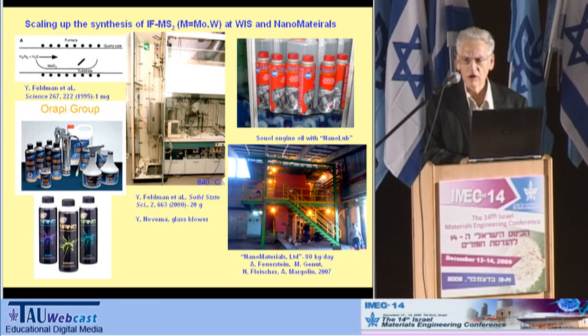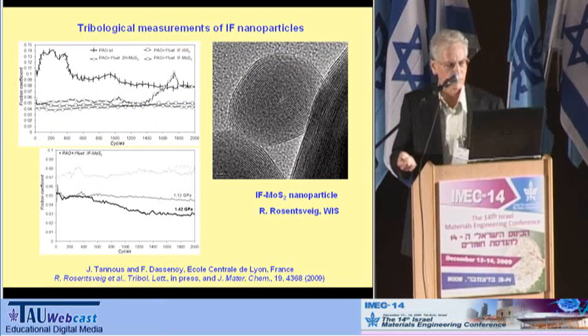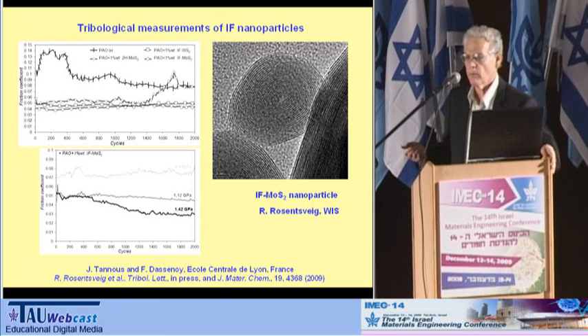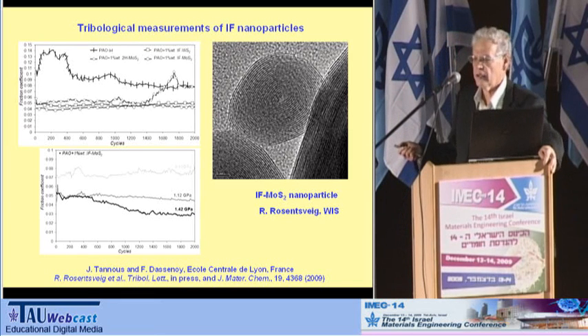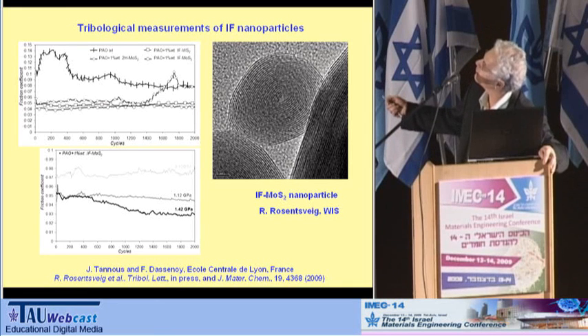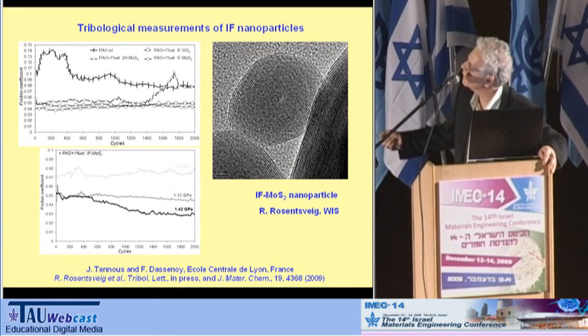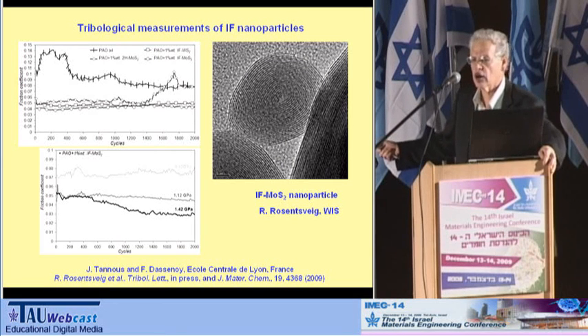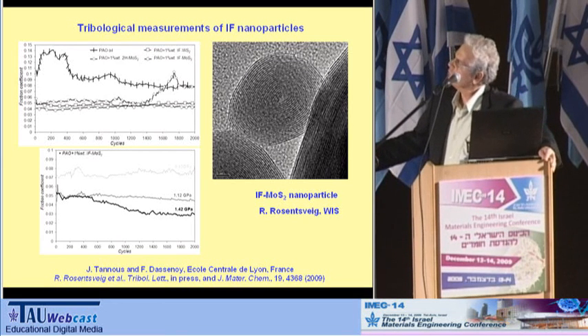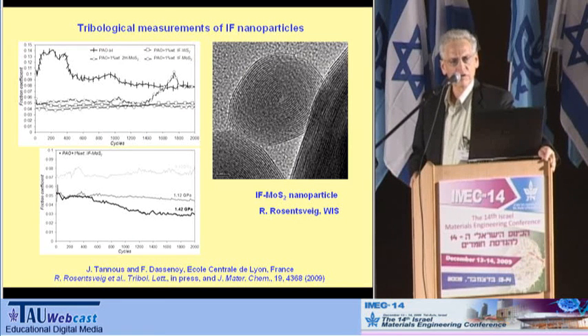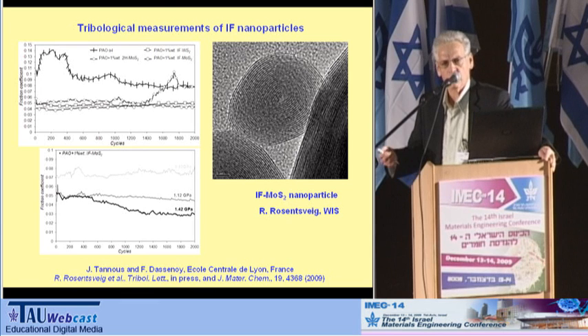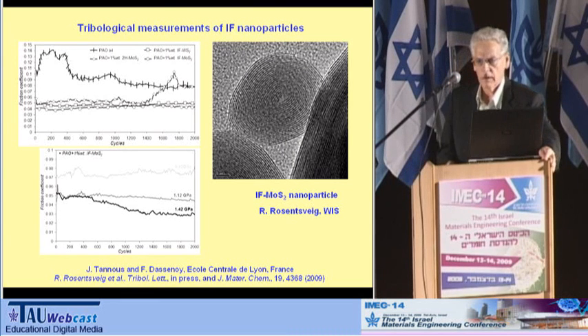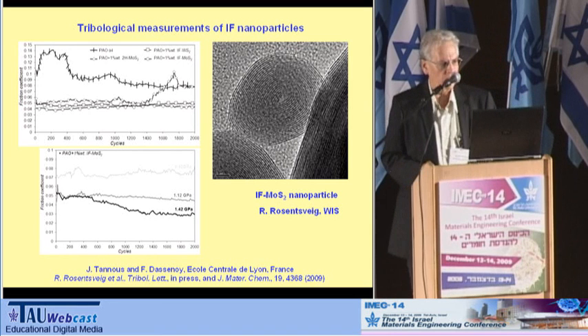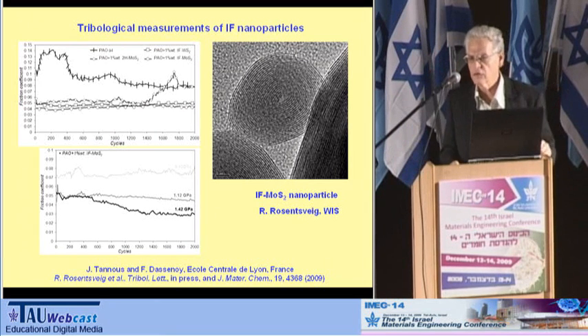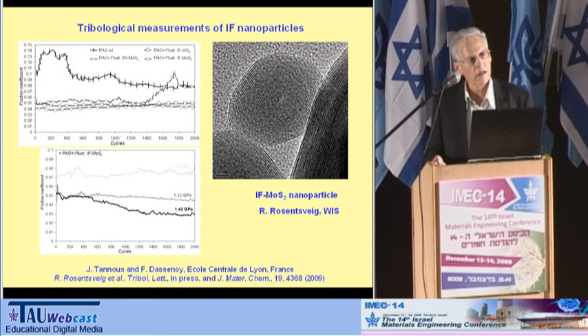So this is a commercially available lubricant now, and this is a work that has been published recently together with the group of Fabrice Dessanoy in École Centrale in Lyon, and it shows that these nanoparticles indeed are very good lubricant. And you see the low friction coefficient under 1.4 gigapascal. A friction coefficient of 0.03 is extremely low, and it shows that this material has a big commercial potential in terms of lubrication.